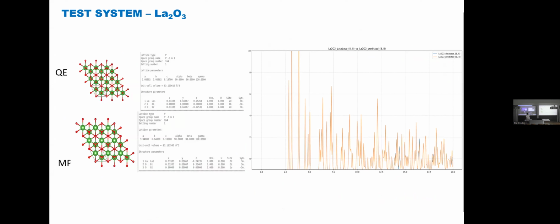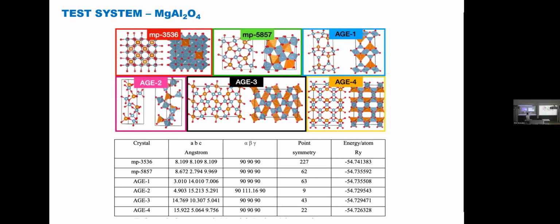Another system, lanthanum oxide La2O3. We wanted to see if it works with huge atoms, and it also worked. We got the structure after Quantum Espresso relaxations, almost the same structure as the reference structure. And then we used a bigger system, magnesium aluminium oxide MgAl2O4. It has roughly 50 atoms in the unit cell, so it was a rather huge system.